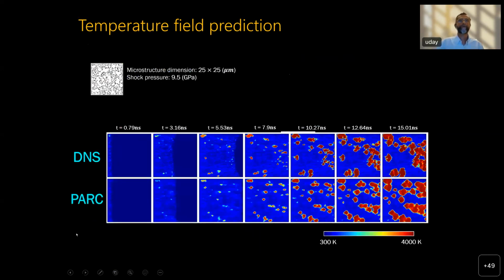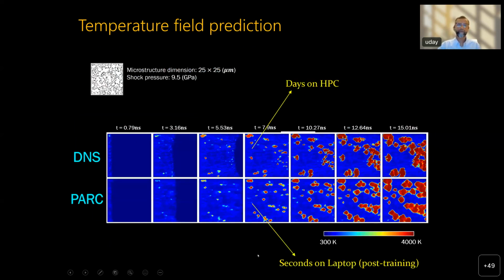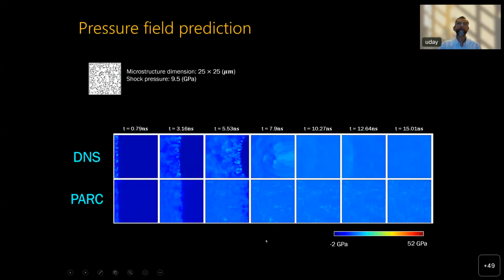So just to show an example of a PARC calculation, the top row is DNS for this microstructure. This is the PARC prediction for that microstructure after training. So you can see that PARC does a good job of predicting what happens, the location of the hotspot, the frequency of the hotspots, and so on. And the advantage is that while a DNS would take days on an HPC, PARC would give a really quick prediction. So it predicts the time evolution of hotspots. And it also predicts the pressure. As you can see, the pressure is not as well predicted as the temperature because the pressure has smaller gradients than the temperature. The temperature is much sharper. But it does a fairly decent job of predicting the pressure evolution as well.